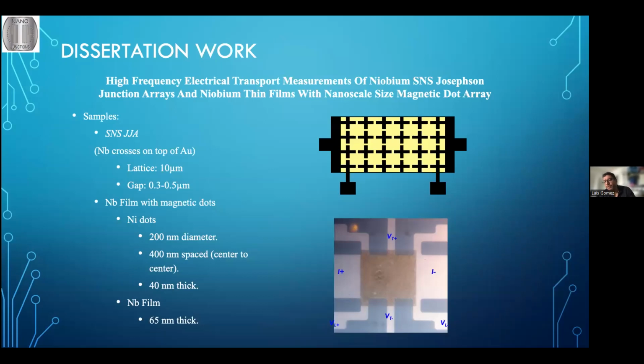So during my PhD thesis, I studied two different systems. The first system here is called an SNS Josephson junction array. It's an array of junctions because each one of these black crosses is an island of a superconducting material. In this case it is niobium, and this niobium was deposited on top of a continuous film, in this case gold.